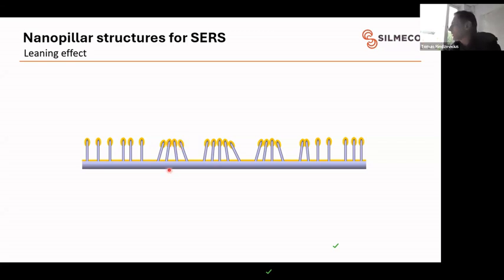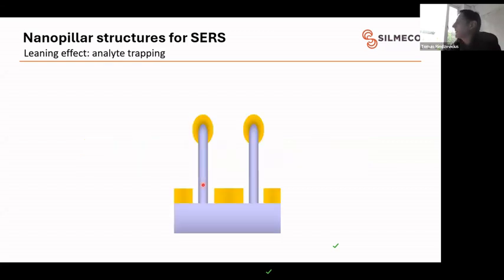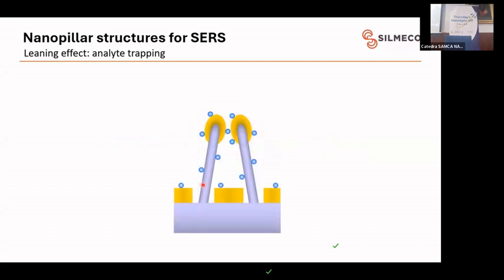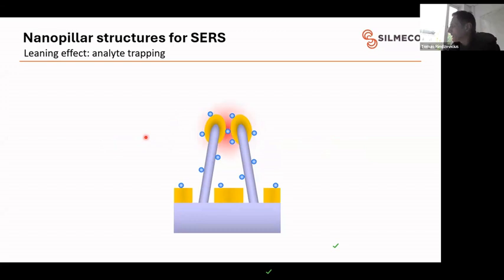And now we have basically created these clusters. But what happens if we have an analyte? This is the same with two pillars, but when we have an analyte in the solution, when it dries, now we have a chance to trap the analytes close to the hotspot. This is what we actually want. And we've done some comparisons, leaning versus non-leaning, and it seems like this is a very important step. Here you can directly see that these substrates, for example, would not be very suitable for gas sensing, because you would probably need to pre-lean them before doing gas sensing. But even if you do that, it would be difficult to get the molecule into the hotspot.